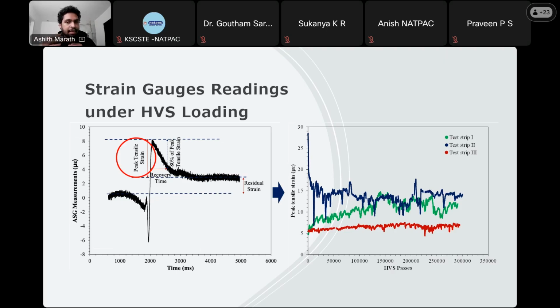and also remember that we didn't find any cracks at the end of 300,000 passes of the loading, but we still used the peak tensile strain values to compare between three different pavement sections, and we found that the ECA pavements either had a comparable peak tensile strain value or even less than the conventional pavement's tensile strain value. So which is best in case of fatigue performance.